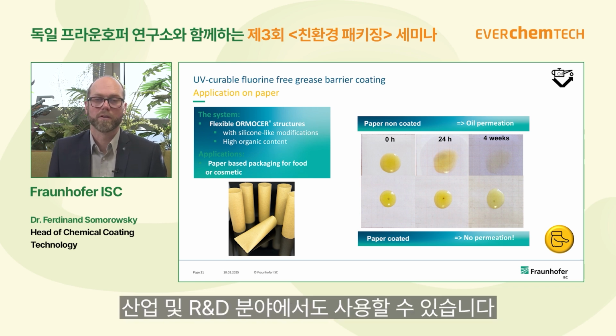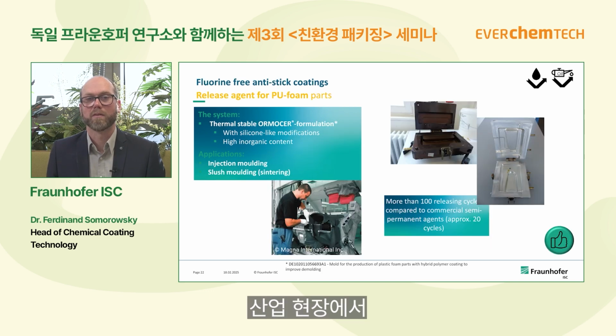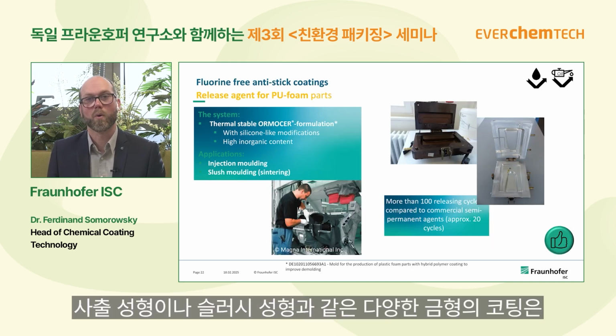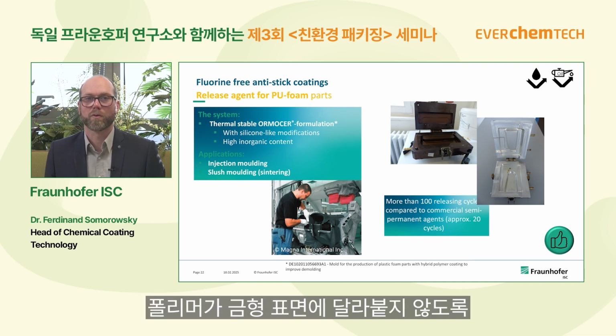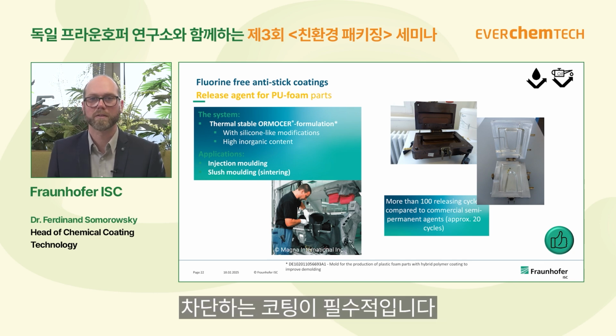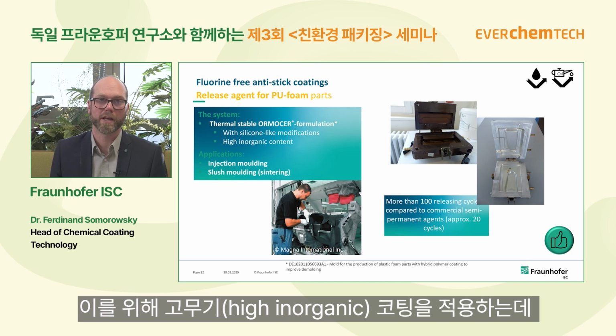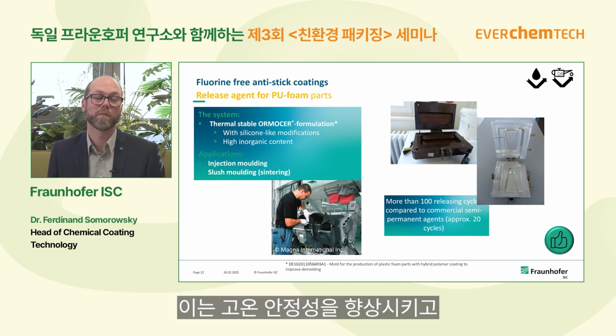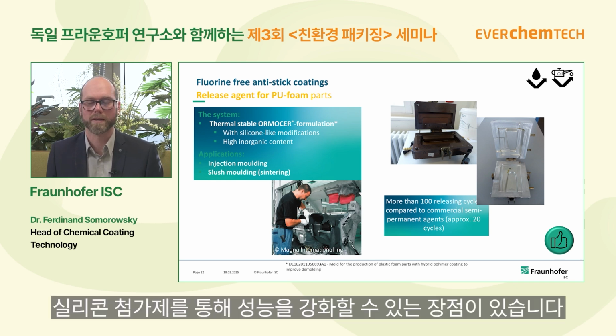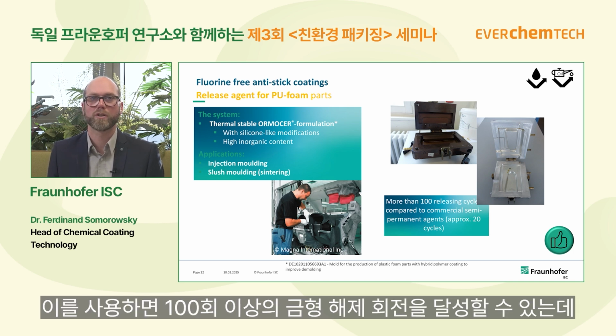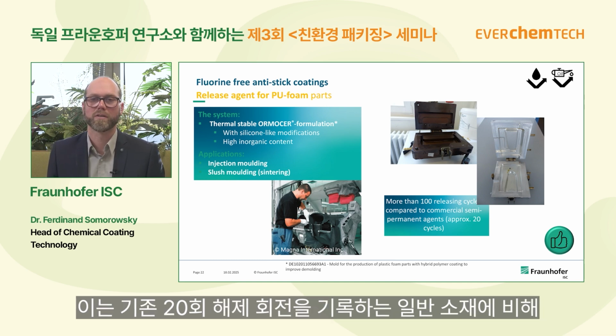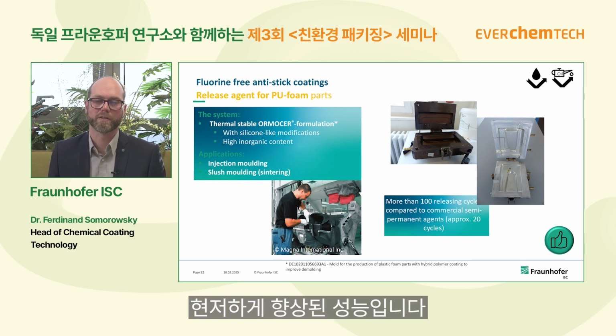But there are also other use cases in the industry and also in R&D. For industry, the coating of different molds, for example injection molding or slush molding, is very important because the polymer should not adhere to these molds. One option is to use the ORMOCER with a high inorganic ratio, because then it has a higher stability towards temperature, and again with silicone additives. And here we can reach more than 100 release cycles in comparison to 20 release cycles with the state-of-the-art material. You have really a good improvement over the state of the art.